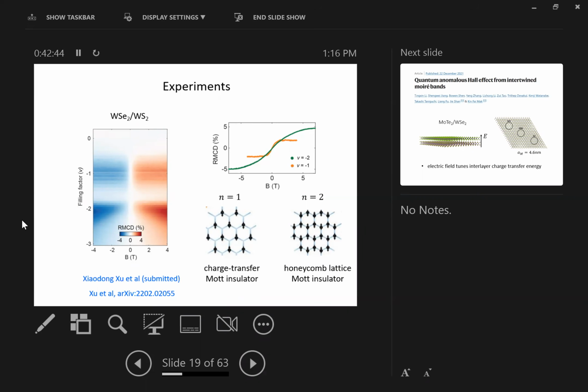Even in this WS2/WSe2 original system, Xiaodong Xu's work looked at the magnetic circular dichroism as a function of magnetic field at different filling factors. At filling factor 1, you see this big contrast. It shows that there is a magnetic circular dichroism in the presence of a tiny magnetic field. That's what we expect from a Mott insulator. But then, interestingly, around filling factor 2, this strong magnetic circular dichroism also shows up. This is something that cannot be understood within the triangle lattice Hubbard model picture, because at filling factor 2 in the triangle lattice, you have to doubly occupy every site. So then there will be no local magnetic moment at all. But this dichroism actually indicates the presence of local magnetic moments.